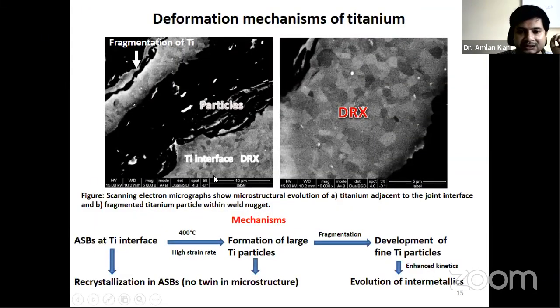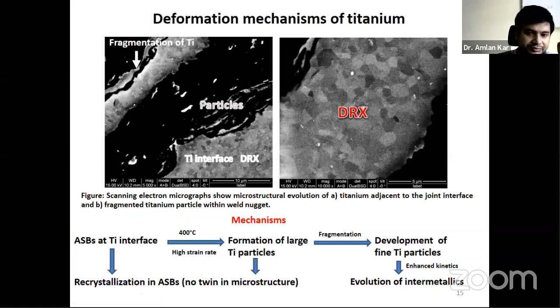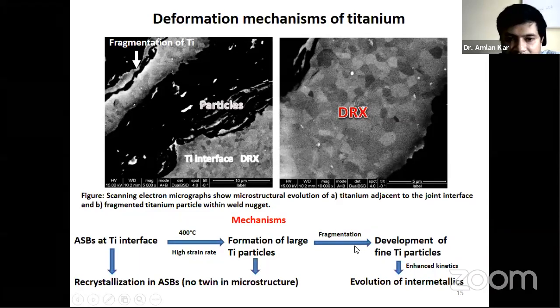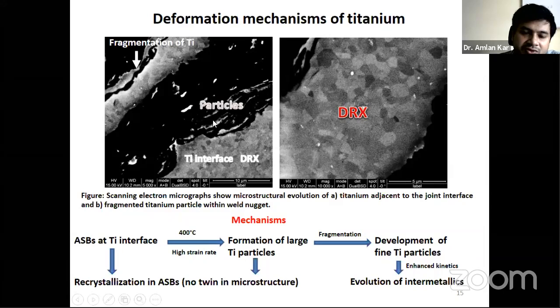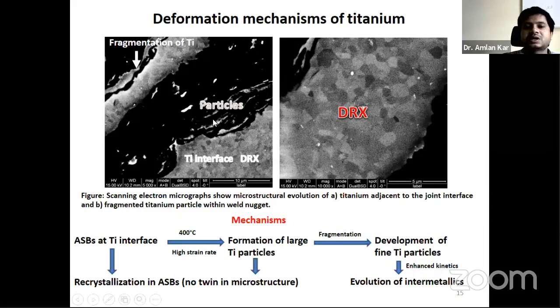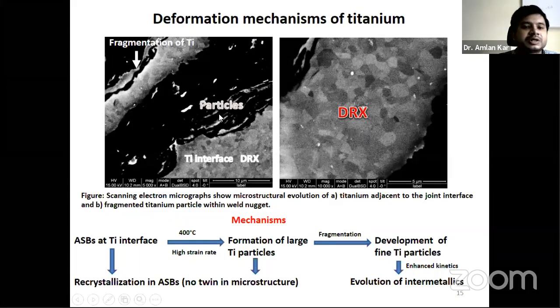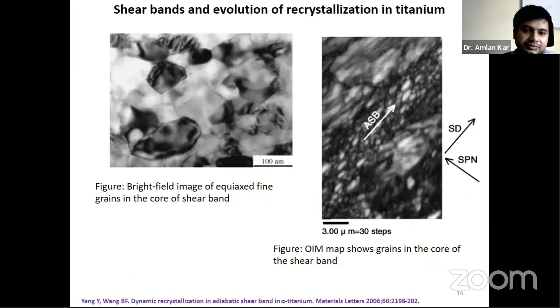As I already discussed, this is the mechanism which leads to the formation of particles as well as recrystallization. When there are very fine particles, there is a higher surface to volume ratio, which leads to higher surface reactions, leading to the formation of intermetallics as well. So a very fine particle is not actually a titanium particle; it is subjected to reaction and leads to the formation of intermetallics.